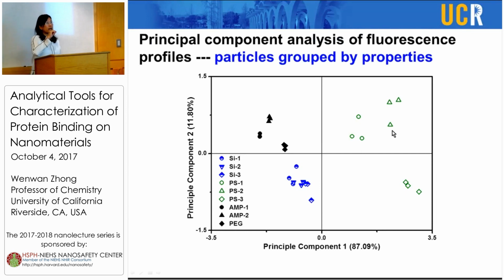The green triangle and the green circle are the 2 polystyrene particles with very close core diameter, like 42 and 43 nanometer. But then the green diamond is the 85 nanometer polystyrene particle, and they are very well separated after we do principal component analysis of the fluorescence profiles, and they're grouped separately.